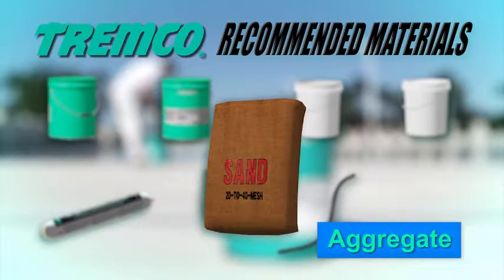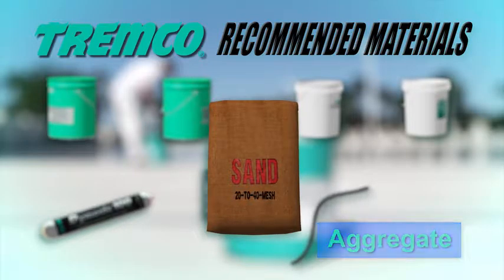The recommended aggregate for use with this deck coating system is a 20 to 40 mesh or 0.6 to 0.9 mm diameter silica sand or aluminum oxide, which imparts a textured finish and contributes to wear resistance.